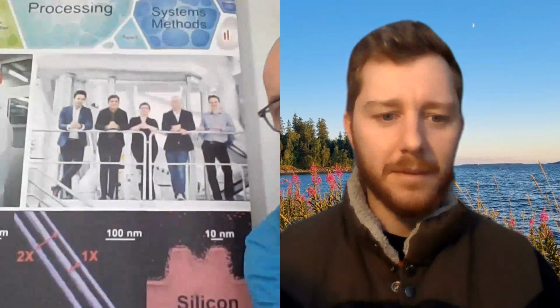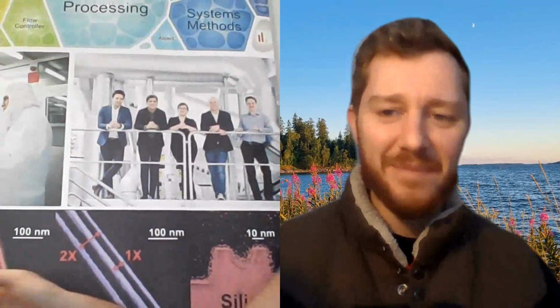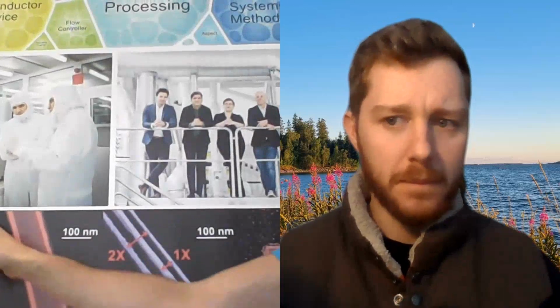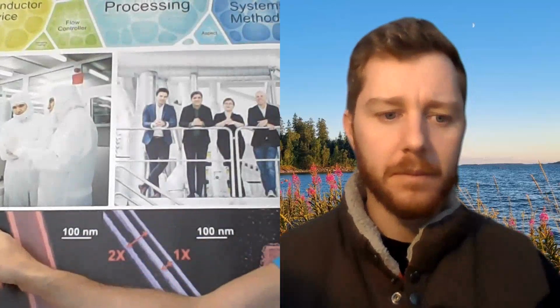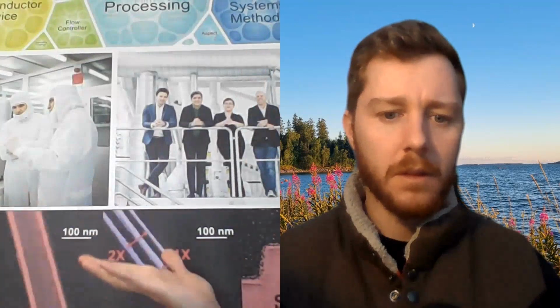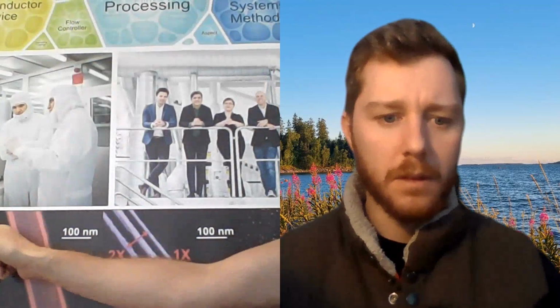So they came out split. Like if you think about the log canoes in the Stone Age, where you chop out the center of the thing. There are some pictures here, so you see they looked like this. You had the original nanowire about 60 nanometers across, and then we etched out the center. So we basically split it into 2 nanowires.